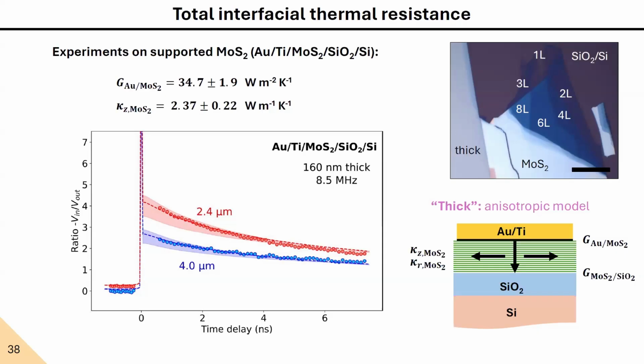The point here is, let's say, a higher temperature and a faster decay would imply a more efficient heat transport. The fast decay is more efficient. Okay. You are increasing the temperature and you are quickly dissipating this thermal energy from the hot spot. So the difference between the hot and the cold is now larger, so a larger signal, and the faster it decays, the better. Exactly. Eventually, if you start having a more resistive behavior, the curve flattens, and eventually the signal will also lower. You start overheating the material, and therefore your contrast between the on and off heating is lower. Perfect.